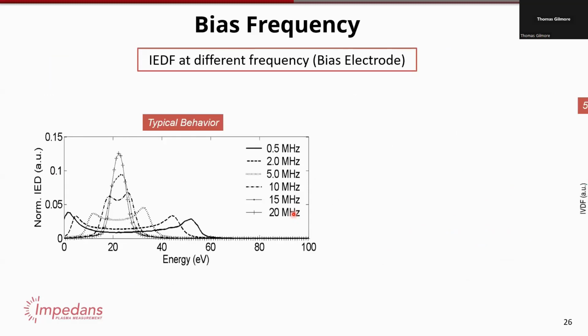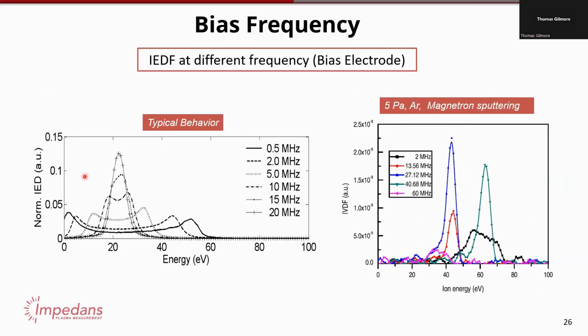Let me just show you practical examples of the different frequencies. This will be important later for the tailored waveform and so on. As you apply higher frequencies, the ions react less, but as you apply lower frequencies, the ions react more. So with the same power, you actually get much higher energies. In this case, all of them have the same power, but you get different responses with the different frequencies. The responses aren't always as clear as this. In a magnetron sputtering system here, the responses are really quite unusual per frequency.